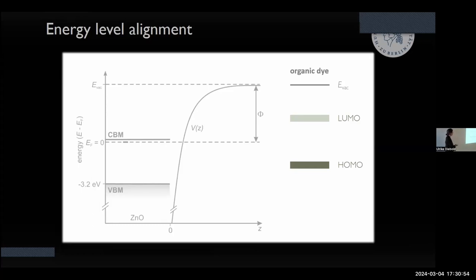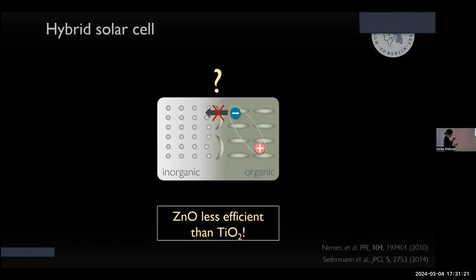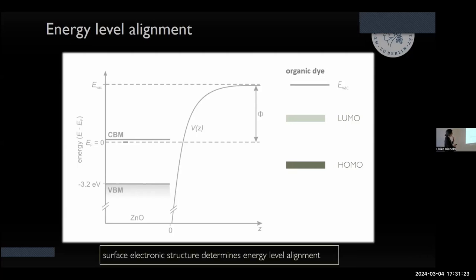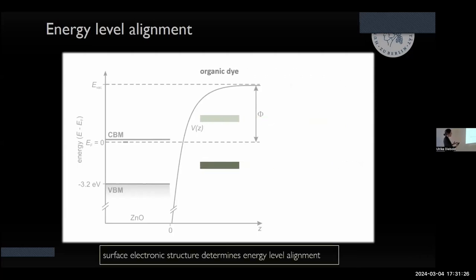So this is a zinc oxide band structure. Then you have this potential step here. It's basically the chemical potential for the chemists. This is the work function. And then we have organic dye molecules, and if they are very far away from each other, you have the vacuum level alignment, and then you bring them together. You will have a bond dipole formation. It's all very complicated. And then you end up with a certain energy level alignment, and then you photo excite your system, and the charge